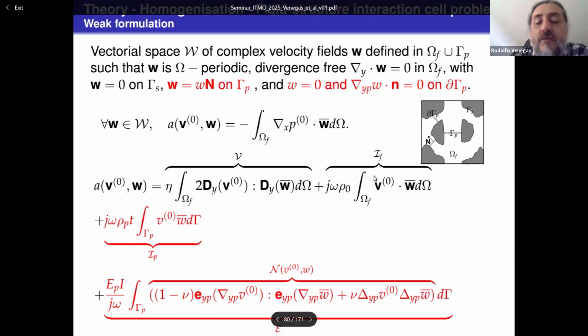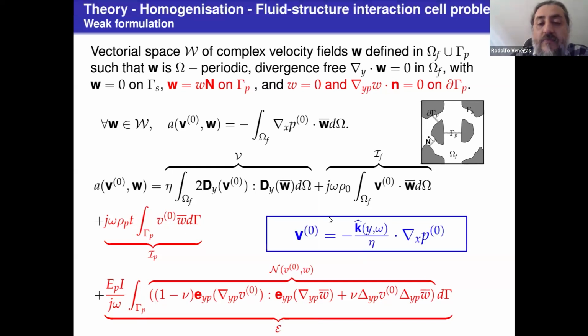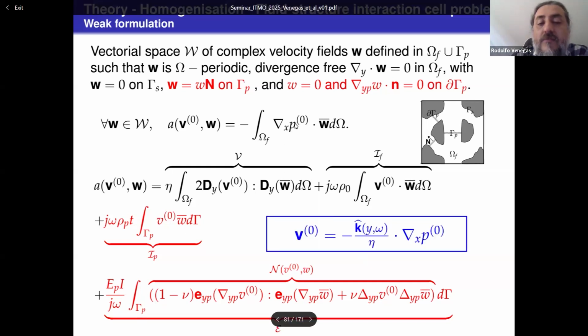So these two terms are the traditional terms related to viscosity and inertia of the fluid, but the presence of these films make these two terms appear. One of them is to do with the inertia of the films or the plates, and the other one is to do with the elasticity. So when the elasticity is compensated by the inertia of the fluid-plate system, we will see resonances. And again, this problem is linear, forced by the macroscopic pressure gradient, so we can write the solution as an operator acting on this external forcing term.